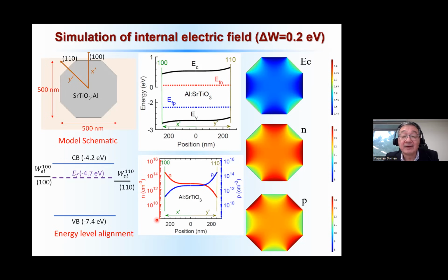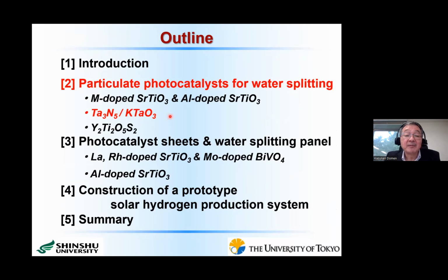And then we also evaluated the ratio of photoexcited electron and hole accumulation. I won't get into the detail of these numbers, but from these numbers, we are sure that photoexcited electrons and holes are separated with almost 100% efficiency. So the origin of the almost 100% internal quantum yield of the water splitting reaction is this type of internal electric field. Now let me move to some different photocatalytic materials.